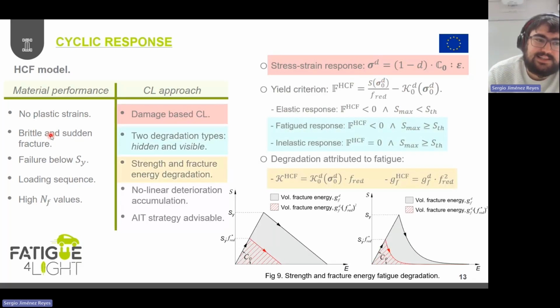Then, as this high cycle fatigue process takes place, or the failure takes place, in a brittle and sudden manner, and as I commented previously, the failure occurs for stresses below the yield strength, this needs to be reflected somehow in a different manner to the way that we used to do for the isotropic damage model. And the way that we achieve that is, first of all, by introducing, in addition to this visible inelastic process that appears in the damage constitutive model, this hidden inelastic degradation process, or this fatigue response.